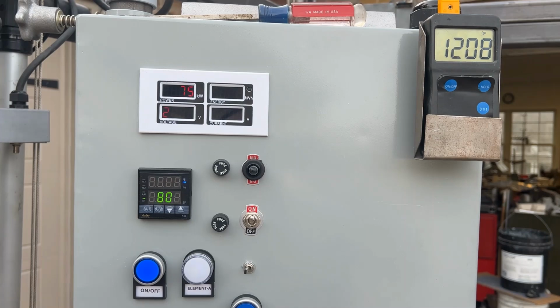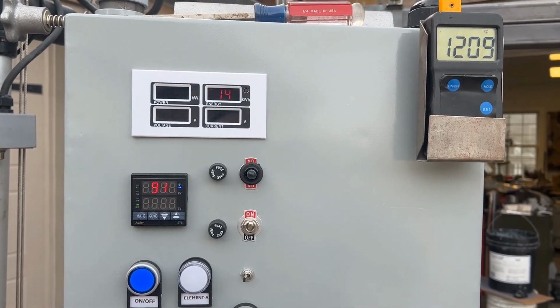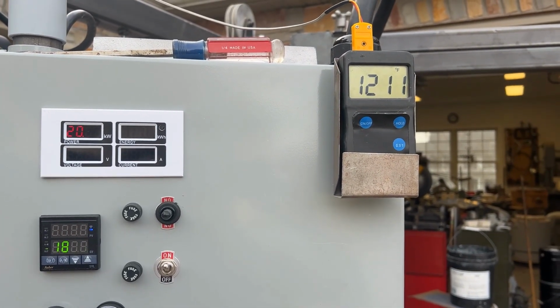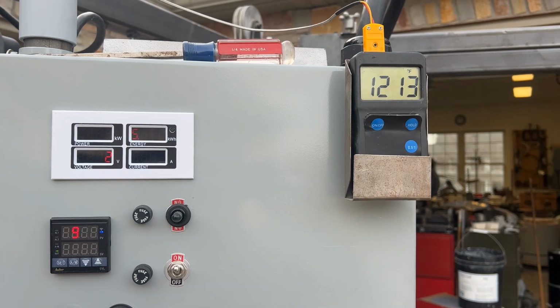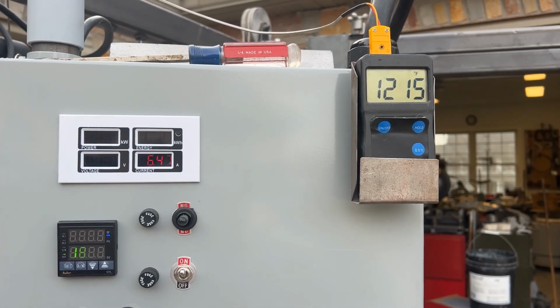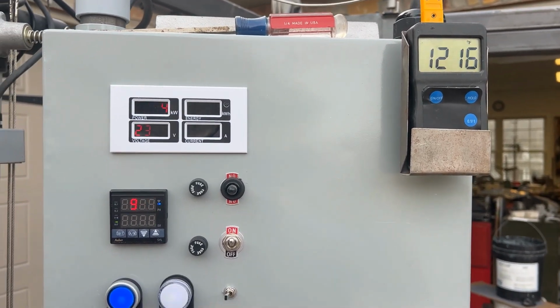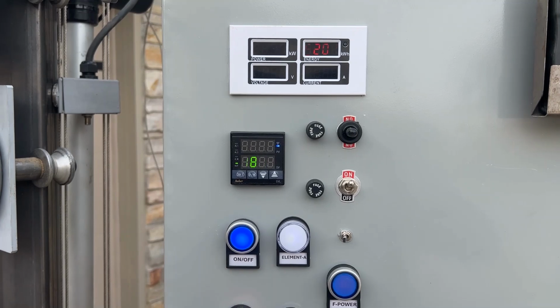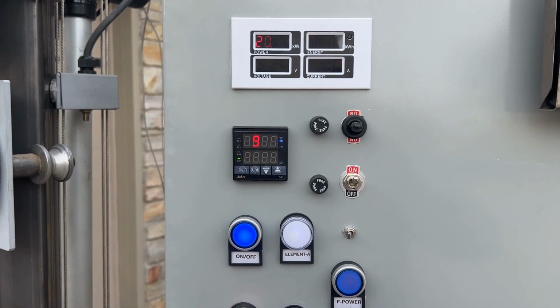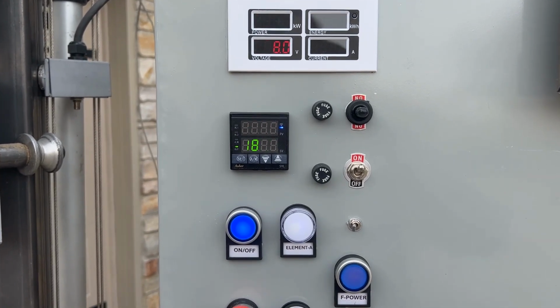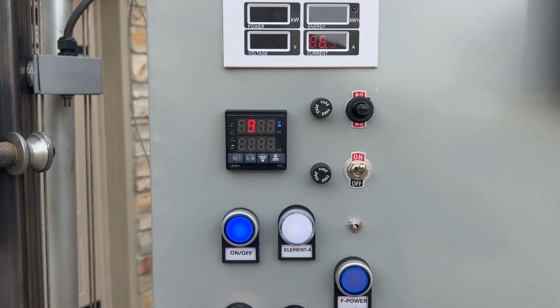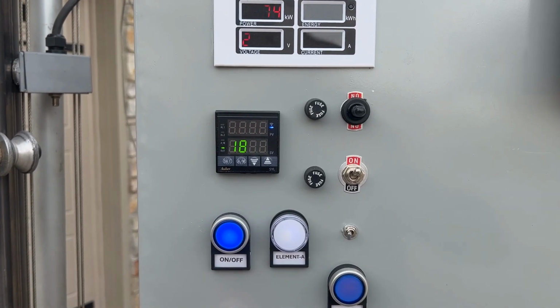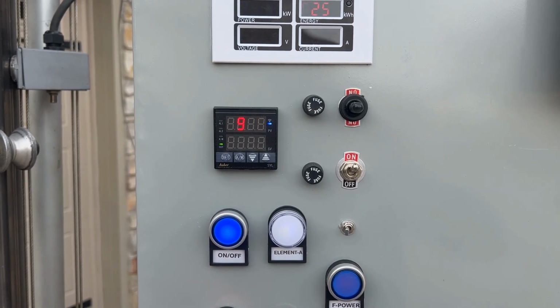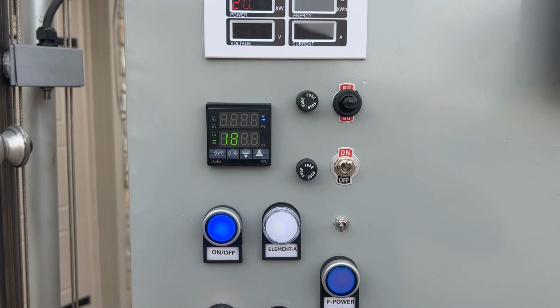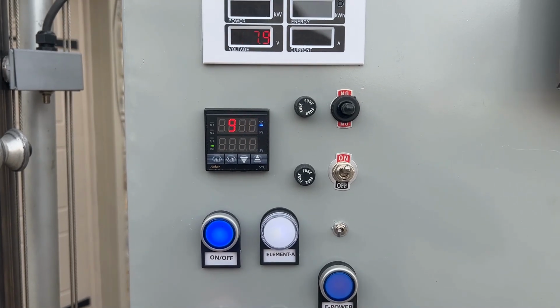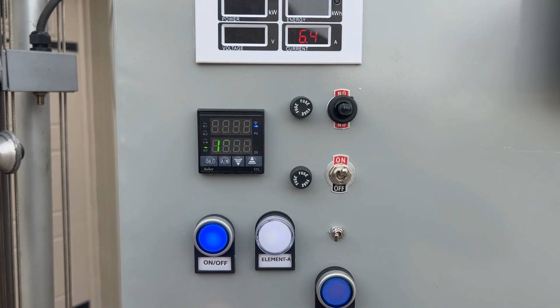Well, I'm sure you probably can't see the PID because it's strobing, but you can see the handheld meter there. That's the gap between the crucible and the wall of the furnace, that's where that's being measured. And the center of the lid is lagging about 300 degrees behind. That's being measured basically at the top of the crucible, where that crucible is full of a 40-pound charge of aluminum.